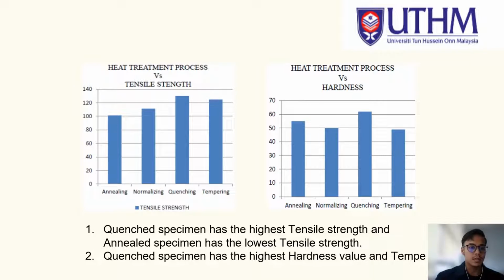We can see here heat treatment process versus tensile strength and heat treatment process versus hardness. For tensile strength, we can see the quenched specimen has the highest tensile strength and the annealed specimen has the lowest tensile strength. For the hardness, we can see the quenched specimen has the highest hardness value and the tempered specimen has the lowest hardness value.